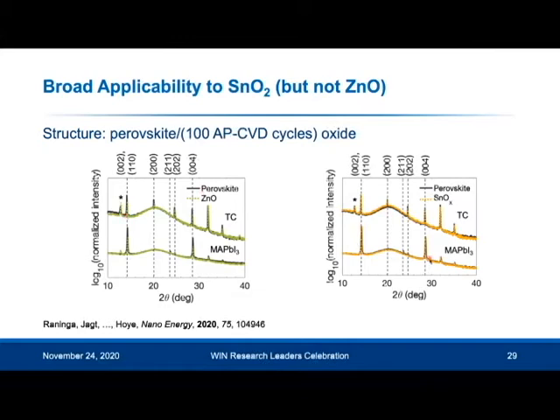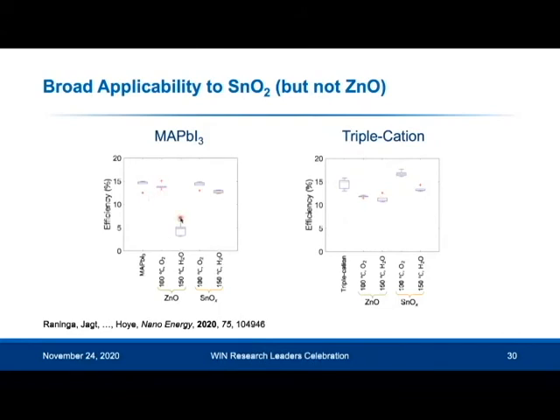So this is consistent with the literature. When we look at the tin oxide, by contrast, there was no extra lead iodide peak. With the triple cation perovskites, the as-grown thin films have residual lead iodide. After growing tin oxide directly over it, after about 2 minutes of deposition, there was no increase in the lead iodide diffraction peak, which shows that there's no degradation of this triple cation perovskite. And consistent with these diffraction results, we found that the efficiencies went down when we were using zinc oxide, but they didn't significantly decrease when we used tin oxide instead. And in fact, when we used a buffer layer of tin oxide grown under mild conditions, we saw an improvement in the efficiency compared to the control, at least for the triple cation devices.